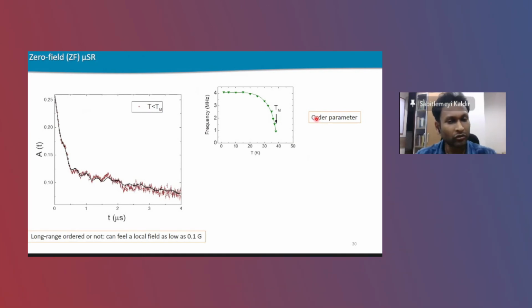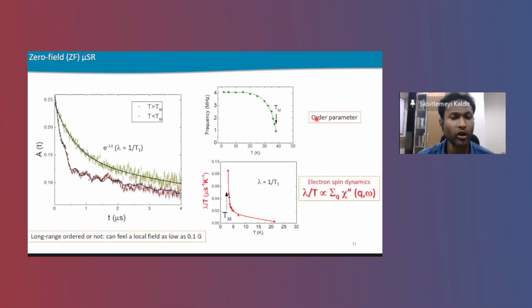Okay, so now forget about the ordered state. In the paramagnetic state, you only see relaxation behavior, and this lambda, that is nothing but 1 over T1, is probing the electron spin dynamics in the paramagnetic state. This lambda over T parameter is proportional to the imaginary part of the dynamical spin susceptibility. So if you plot lambda over T as a function of temperature in the paramagnetic state towards the ordering temperature, you would expect that it is going to follow some power law behavior. This is very important in order to understand the data that I am going to show you in the upcoming slides.